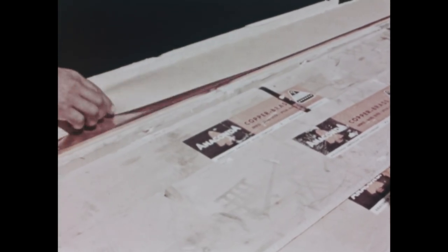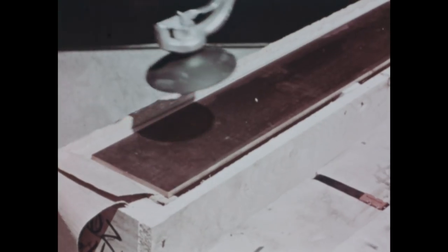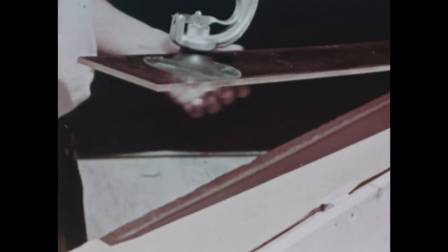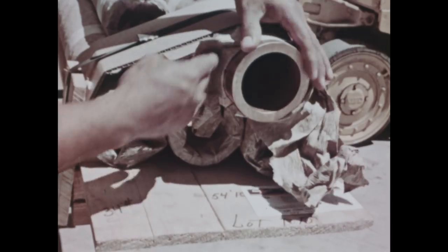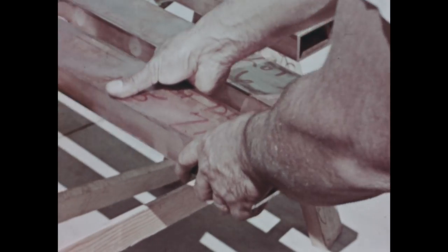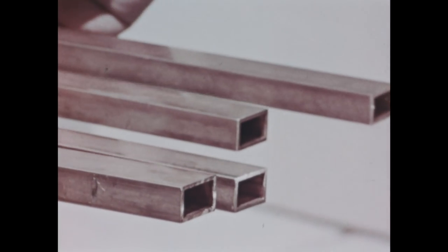Waveguides are conductors of electricity and must be made of highly conductive material. Nearly two million pounds of refined copper is being processed to eliminate virtually all impurities. This oxygen-free, high conductivity copper is then formed into flat bar a quarter of an inch thick, extruded pipe four inches in diameter, and other extruded pieces to form the rectangular waveguide and cooling systems.